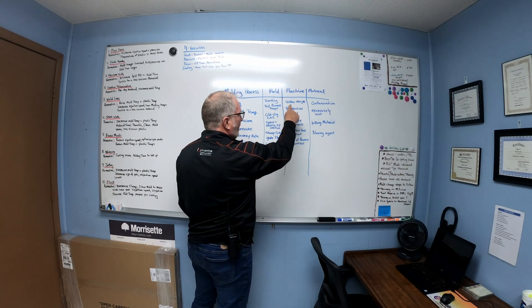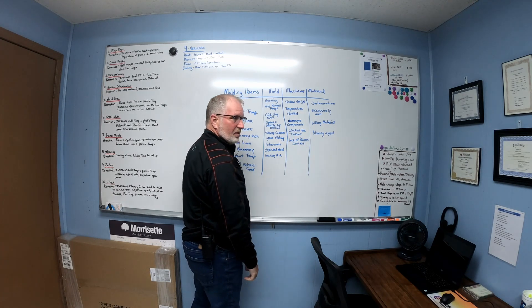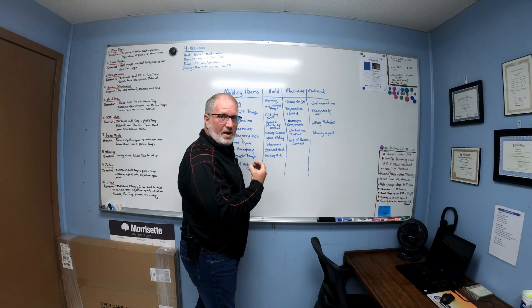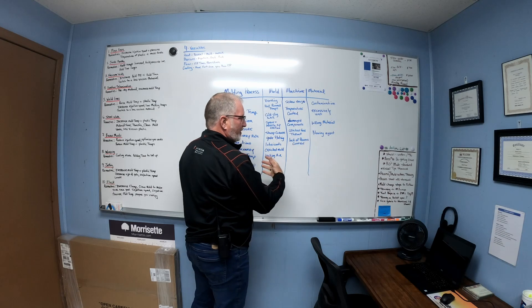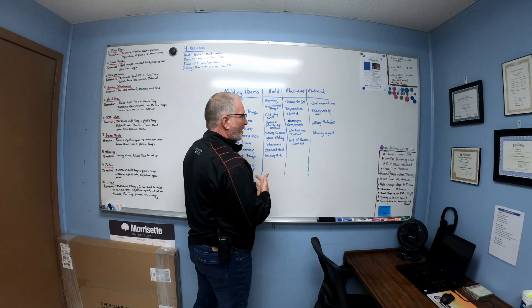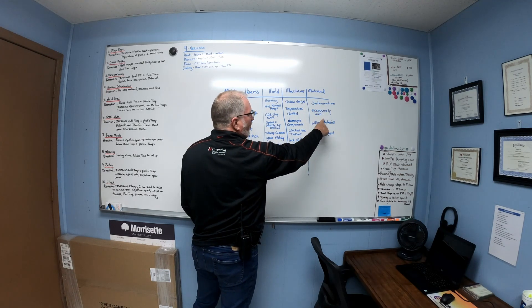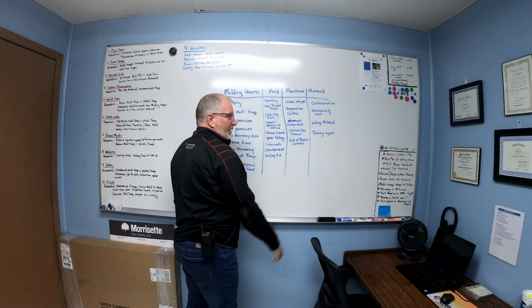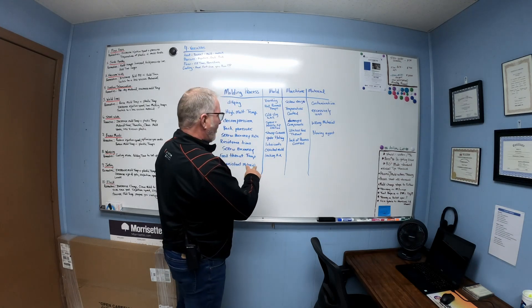On the machine side: screw design, temperature controls, damaged components on the press, and a cracked feed throat — you could be getting water into your material without knowing it. Lack of process control — if you can't control injection speed or pressures — is also a factor. For the material side: contamination, excessive wet material, wrong material, or blowing agent added in error.